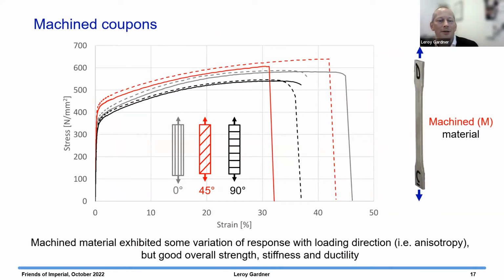Here are some typical stress strain curves. You can see the results for the coupons in the 0, 45 and 90 degree directions. Generally the mechanical properties were good, with some degree of anisotropy, so different characteristics in different directions, but overall good strength, stiffness and ductility.